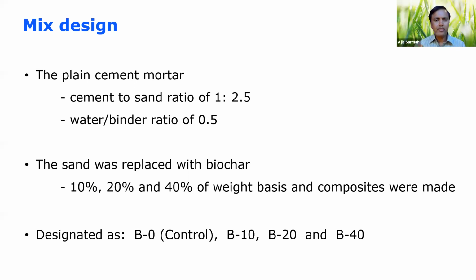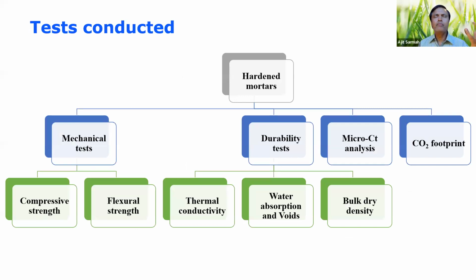Three things: sand, cement, and water, and some aggregates, right? Now, what we did in this particular study, we actually replaced the sand with biochar. And then we designated that as control B10, B20, B40. And then we made some mortars, hardened mortars. And then we looked at mechanical tests, looked at the compressive strength, flexural strength.